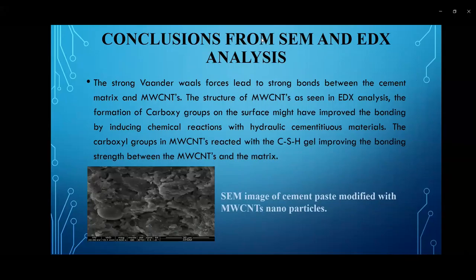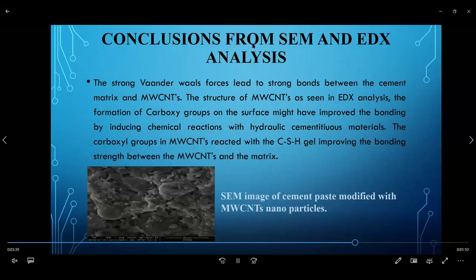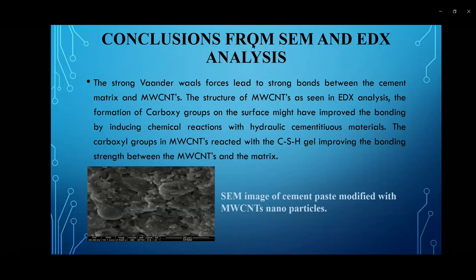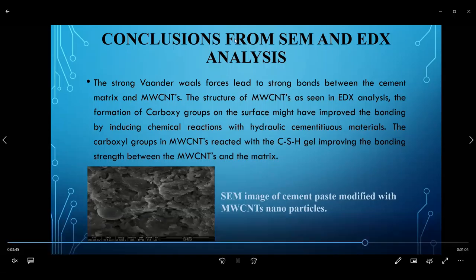The strong van der Waals forces lead to strong bonds between the cement matrix and MWCNTs. The structure of MWCNTs as seen in the EDX analysis, the formation of carboxy groups on the surface might have improved the bonding by inducing chemical reactions with hydraulic cementitious materials. The carboxy groups in MWCNTs reacted with the CSH gel, improving the bonding strength between the MWCNTs and the matrix.